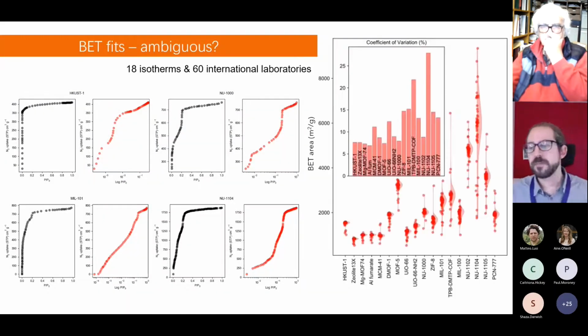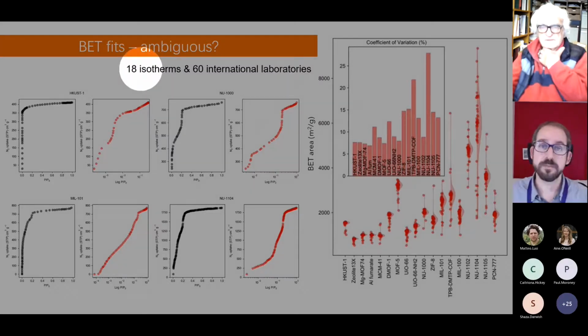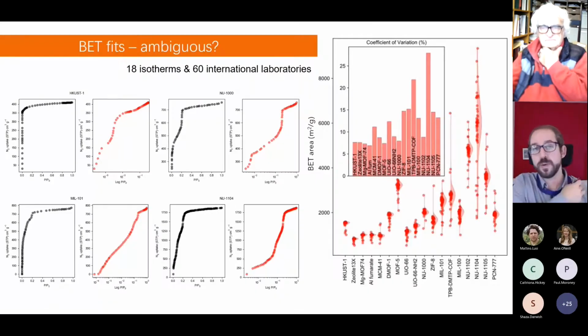So we said, okay, how can we analyze this problem? And what we decided was to collect 18 materials. We measured in our labs the adsorption isotherms, and we sent the data, not the materials, the data, the isotherms already measured in our lab, to 60 international laboratories. We said, can you calculate with this equation, with this data, with this adsorption isotherm, the BET area? Can you apply BET area in the best way you can think of?